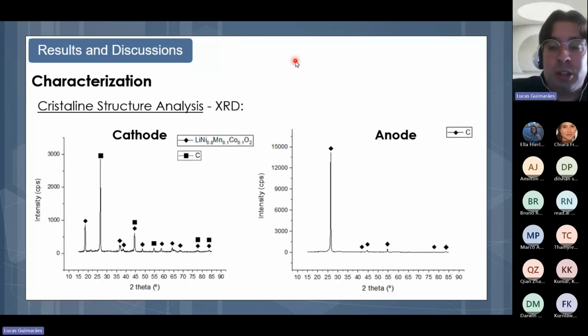Now, talking about results and discussion of the work, after fully and properly discharging the battery with the nickel chromium wires, X-ray diffraction told us that in the active material of the cathode of the battery, we could find this crystalline structure, lithium nickel manganese cobalt oxide, and for the active material of the anode, we could find carbon in the form of graphite.